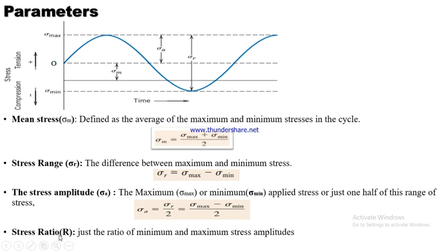Then we have what we call the stress ratio. The stress ratio can be defined as the ratio of the minimum stress to the max stress, which we represent with a capital R: min stress over max stress gives us the stress ratio, which is represented here on the profile. So all these parameters can be seen in the cyclic stress profile.